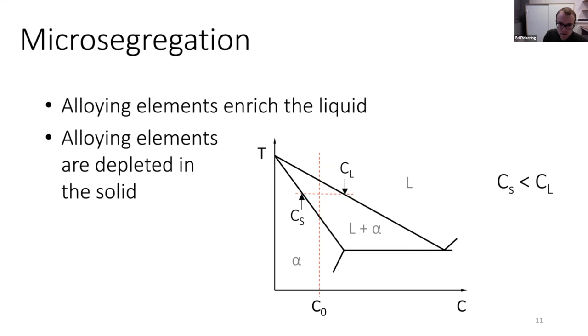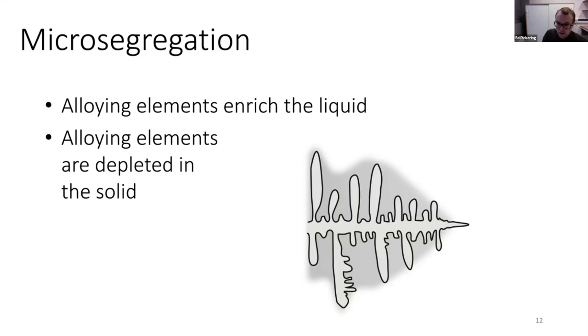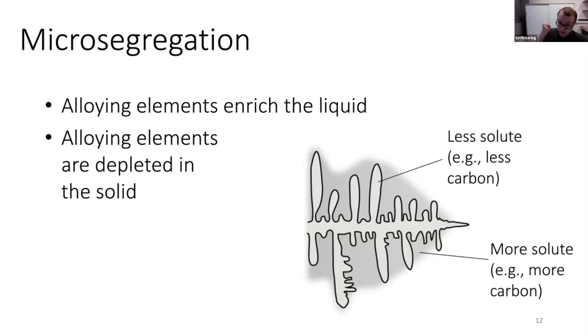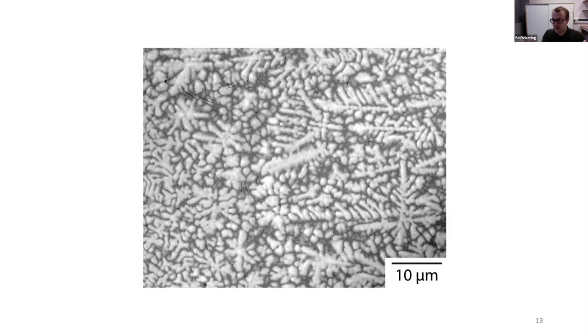In other words, if we have a dendrite, we have our mushy zone, the liquid will be enriched and the solid that it's in contact with will be depleted in solute, in the alloying elements. If you freeze that and just consider microsegregation, this is a sort of pattern that you might see. So you have enriched interdendritic liquid and depleted dendrite arms.